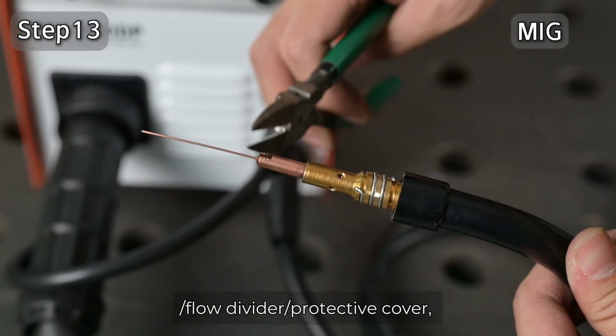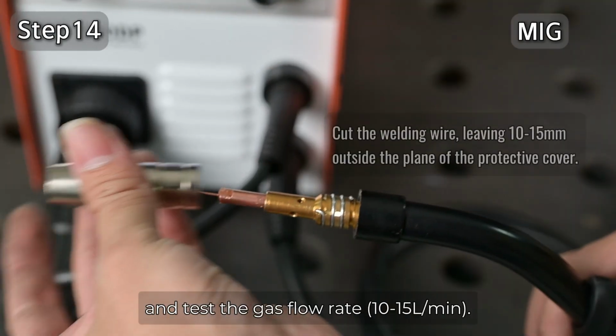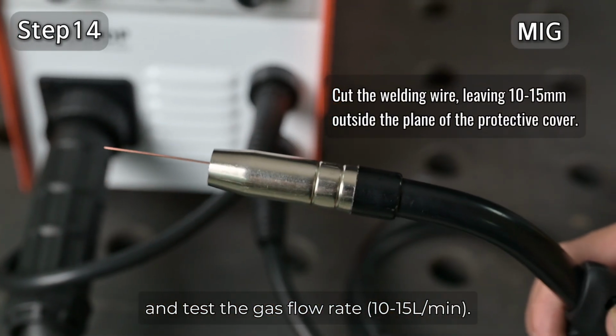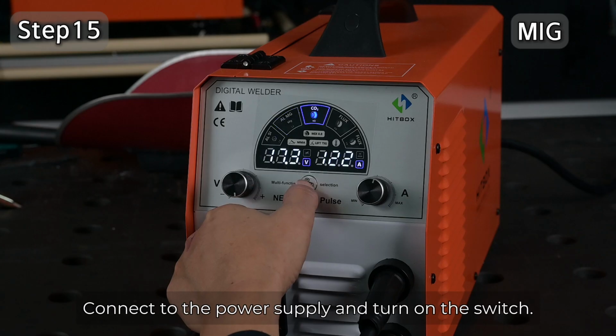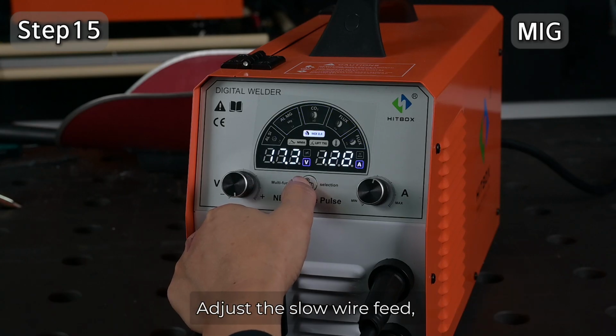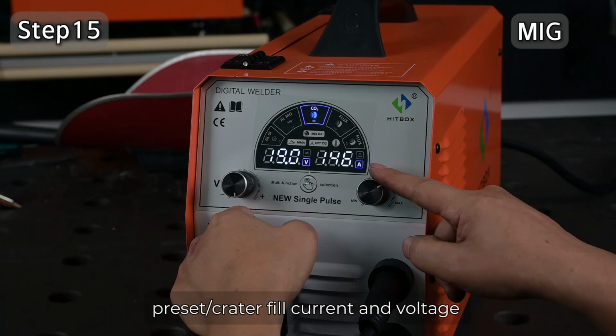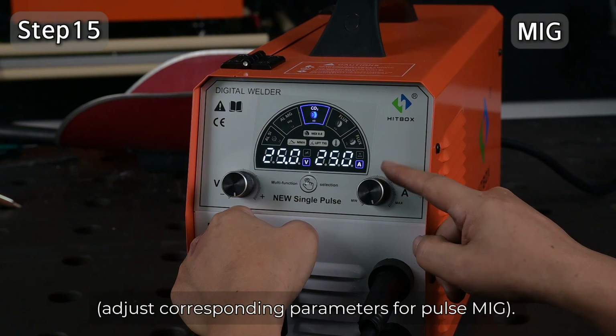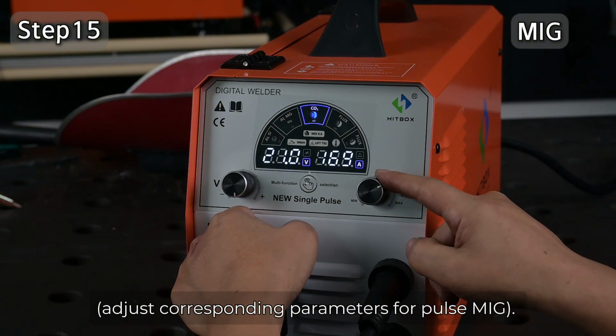Install the contact tip, a flow divider, protective cover, and test the gas flow rate, 10 to 15 liters per minute. Connect to the power supply and turn on the switch. Adjust the slow wire feed. Preset a crater fill current and voltage. Adjust corresponding parameters for pulse MIG.